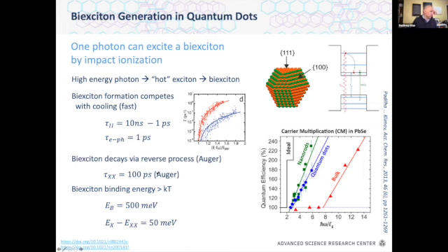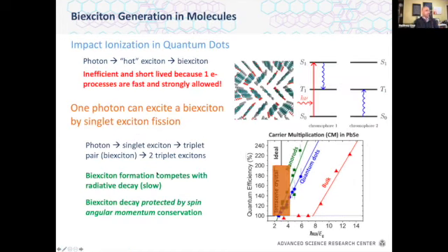Okay. So what are we contrasting with in the molecules? Well, with molecules, we really have to consider spin. And what spin ends up doing is offering protection against competing one electron decay processes. So if we say that impact ionization happens under sort of high photon energy conditions, it's inefficient, and our Biexcitons are short-lived, in our organic molecules where we have an analogous process called singlet exciton fission, we put a photon in, we create a cooled singlet exciton. Our cooled singlet exciton can relax to a triplet pair, and our triplet pair can dephase, and I'll show you later, do other things as well.